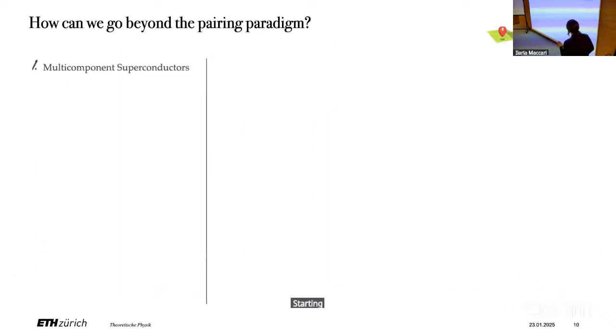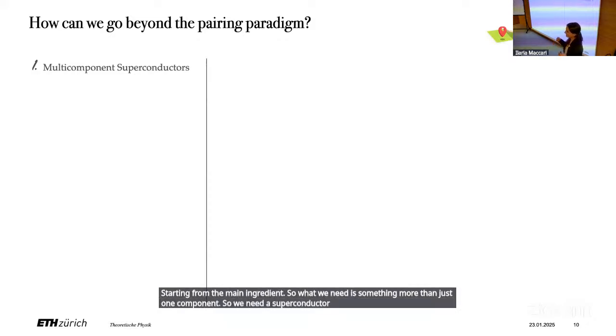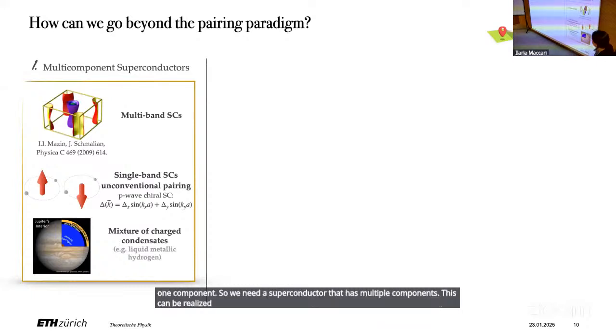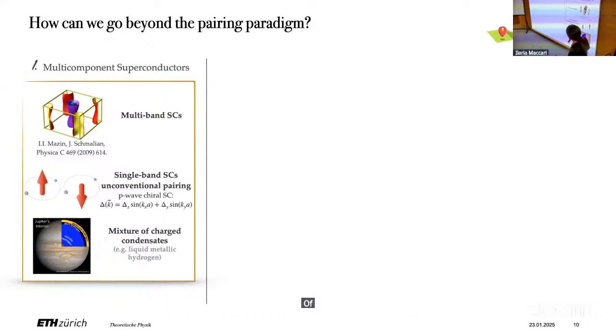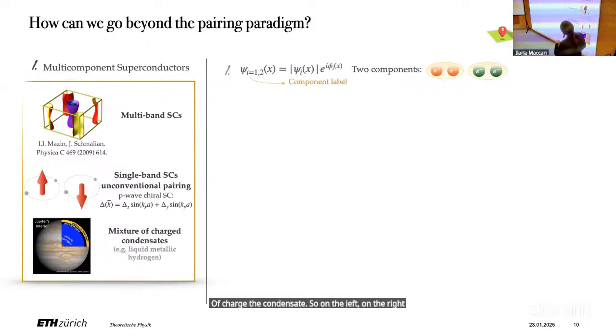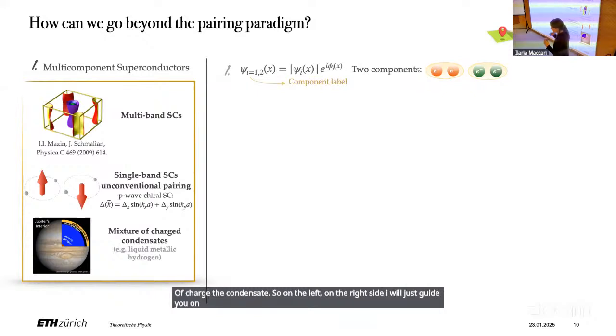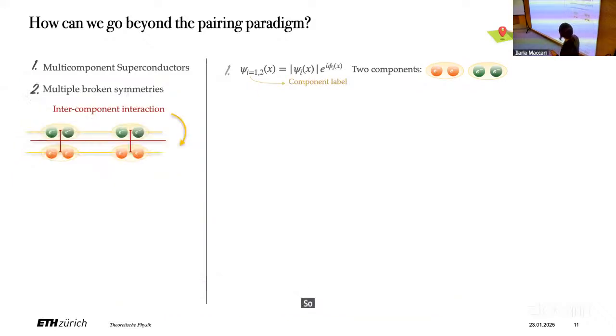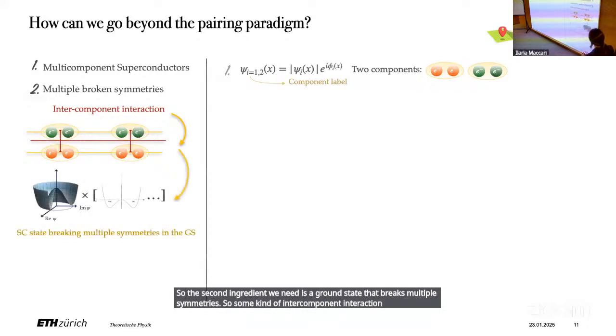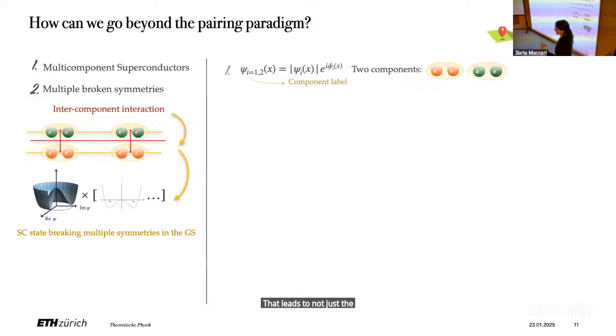Starting from the main ingredient. So what we need is something more than just one component. So we need a superconductor that has multiple components. This can be realized in many ways. It can be the case of multi-band superconductors, single band with unconventional pairing, or even mixtures of charged condensates. So on the right side, I will just guide you through a very simple example to show you the mechanism by which these new phases can be stabilized. So here I just write the order parameter for 2 components, for these 2 species of Cooper pairs, psi1 and psi2. So the second ingredient we need is a ground state that breaks multiple symmetries. So some kind of intercomponent interaction between the 2 that leads to not just the U(1) symmetry being broken spontaneously, but something else.